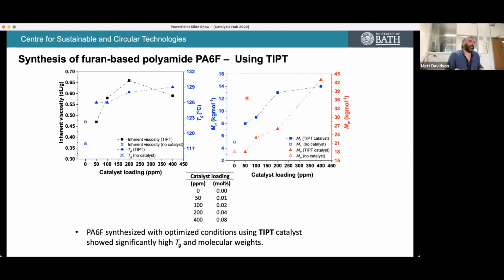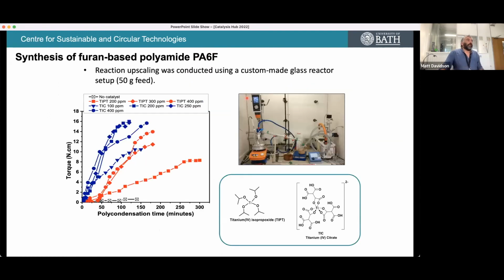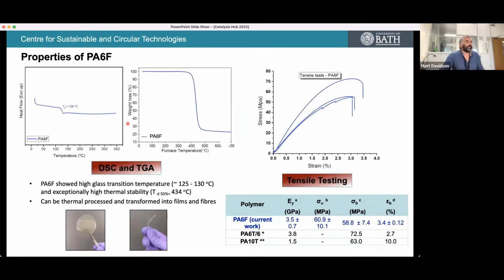Well, both molecular weights are pretty good. We scaled this up, and in fact, we scaled it up further, probably to a significant number of kilograms for similar ones now, Cameron, I think. But we can scale this up to a reasonable level, and then we're looking at the titanium citrate catalyst here as one of the best ones, where we use torque here as a proxy for intrinsic viscosity and therefore molecular weight. So we can make high molecular weight polyamides using very small loading of titanium catalysts for the first time.